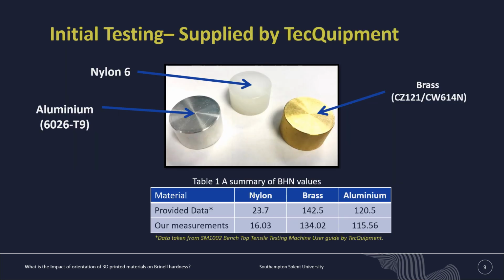Initially, we tested aluminium and brass. This was primarily to practice our method with the hardness test for PLA. We managed to obtain accurate results for both brass and aluminium within 10% of the provided data.